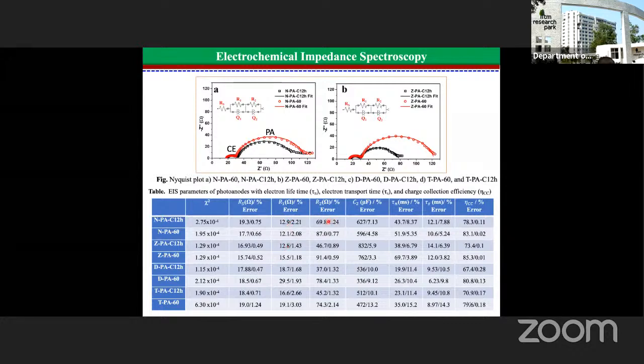The R2, which is responsible for the photoanode—there is a significant increase in R2 whenever we do the dye coating by electroabsorption process. That means the R value increases, meaning the recombination resistance increases, meaning the resistance for recombination goes up, so recombination is reduced. That's what I see in every case here—there is an increase of at least 2 times. And you can also see the tau n, the electron lifetime.